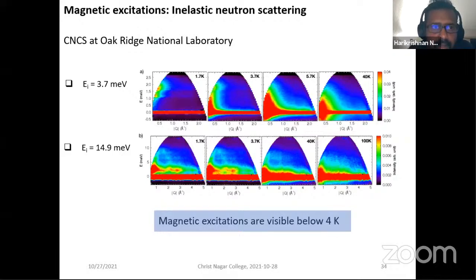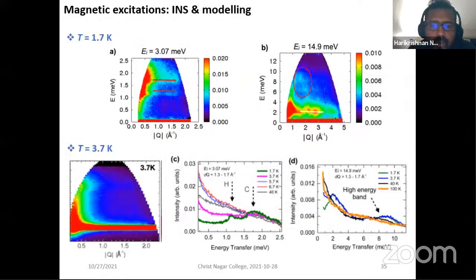There are ways of analyzing this data, and we have done it quite a bit. What we have found is the following: there are 2 energy levels or energy bands that we can distinguish. If you look at panel A on the top at 1.7, you see 2 major peaks starting from the red part in the graph. Those are the 2 energy levels, corresponding to about 1.2 meV and about 1.8 meV. So there are 2 energy bands that exist in the system.